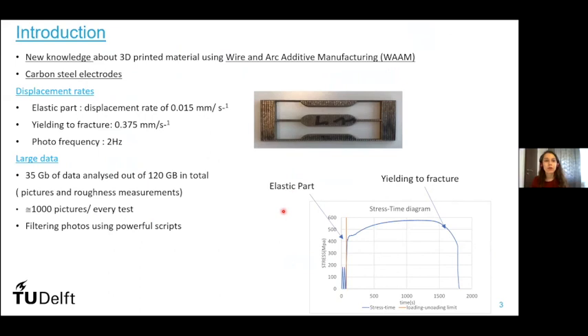This research brings new knowledge about 3D printed material using wire and arc additive manufacturing, but this time using carbon steel electrodes. This is one of the first attempts to use carbon steel electrodes and not stainless steel. For the test, for the elastic part, we used a displacement rate of 0.015 millimeter per second, and in the yielding to fracture part, I used the 0.375 millimeter per second displacement rate at a photo frequency of 2 Hertz. Which means, of course, that I had to work with a huge amount of data. I personally analyzed around 35 gigabytes of data out of 120 gigabytes that were made for the whole project. I had around 1000 pictures for every test, and I had to filter the pictures, of course, so that the analysis won't last that long.